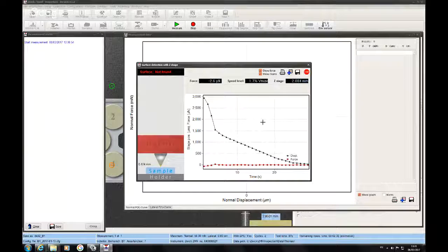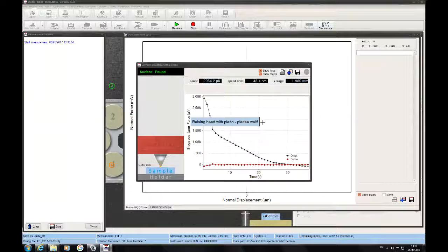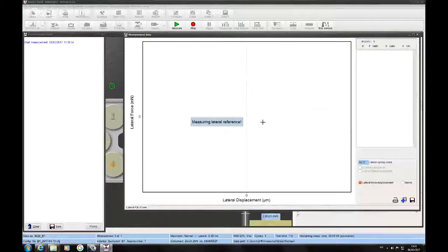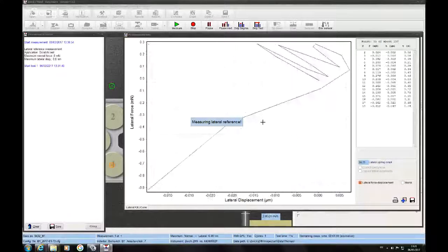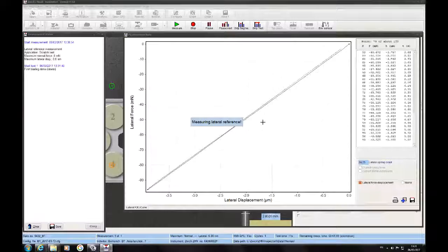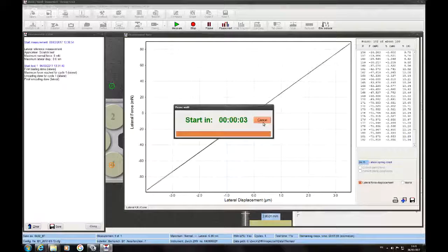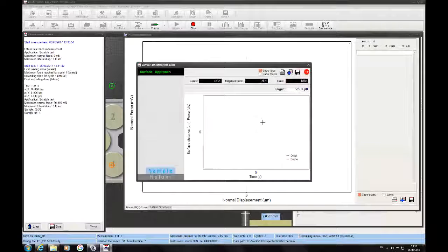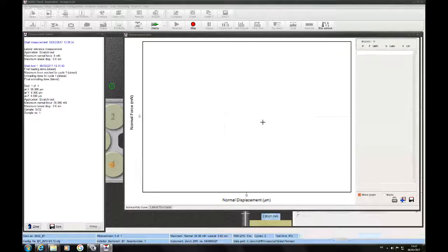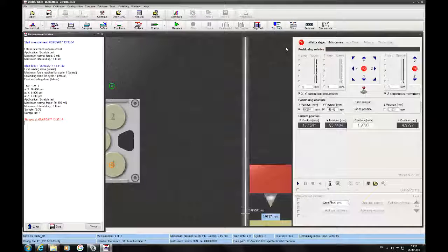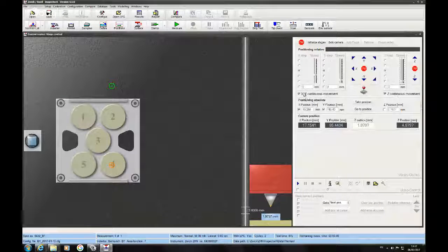So this sample is a little bit deeper than the previous one. So it will not find the surface at 0, but you will see maybe 200 micron or 70 micron deeper. Now this is the measurement against air. Oops, there was a small vibration at the beginning. So here the vibration is not disturbing the result. It only uses the slope of this curve to get one spring constant. We don't need the details. Oh, here was one approach problem. I will try again.